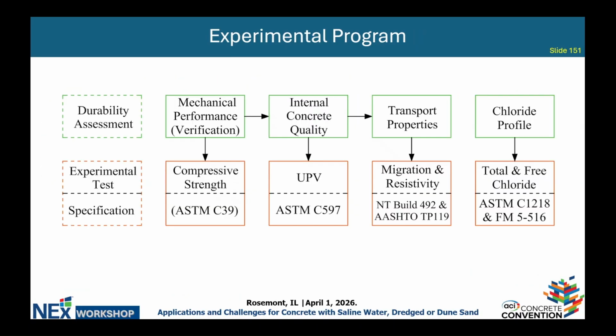So here is a brief experimental program, the preliminary experimental program that we set, because this study is in progress. We started with the mechanical performance verification to determine the evolution of the compressive strength values with time. Then we focused on the internal concrete quality by running the ultrasonic pulse velocity to determine the homogeneity of the concrete material. After that, we used the transport properties, including migration coefficient as well as the bulk resistivity, to indirectly relate to the durability performance of the material.